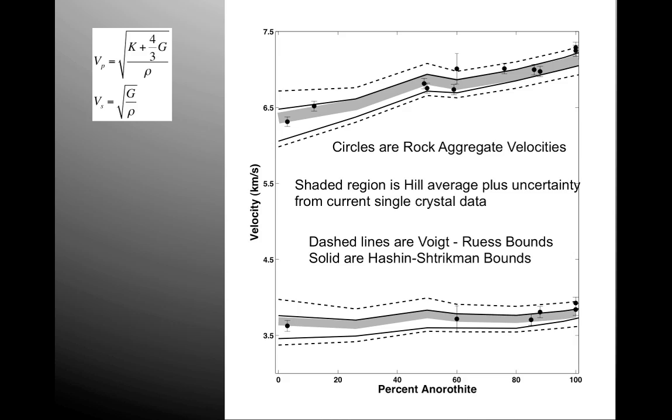Let me emphasize that up until this data set, there has been a long-standing controversy in the community in which rock physics measurements did not seem to agree with the Russian, 1964 vintage plagioclase feldspar data. In fact, it had led a number of people to suggest either that the pseudo-single crystal data had a systematic bias, or that the Voigt bound was preferred to the Reuss bound in estimating aggregate properties.